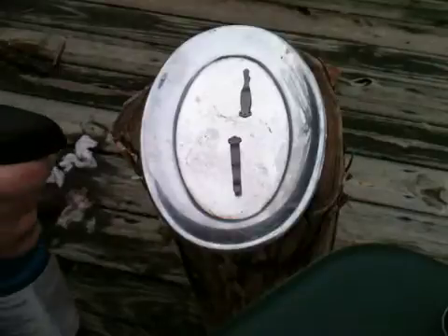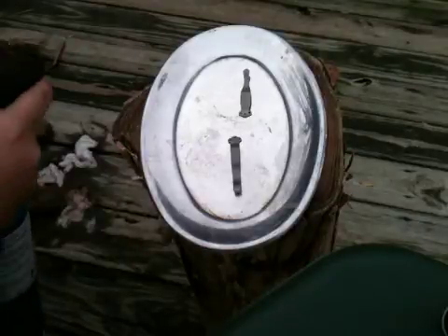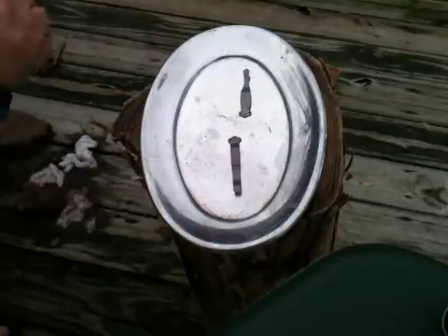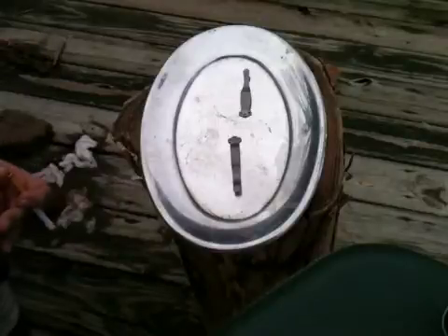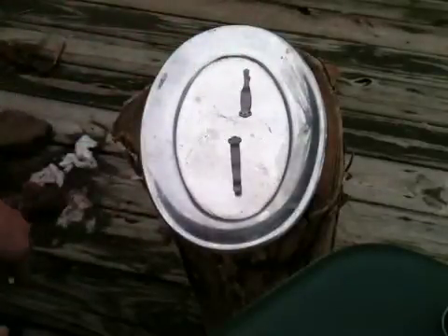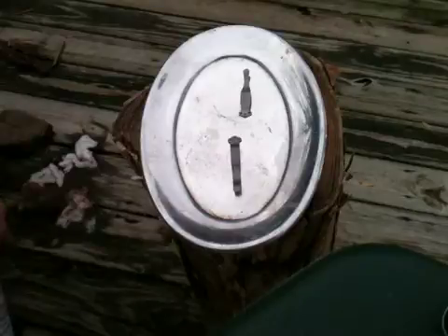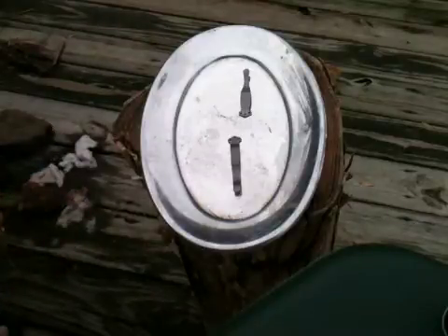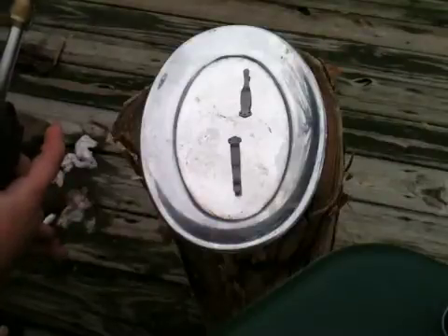Anyway, let's get right into it and see what we can do. I'm going to go for blue. One thing I didn't mention in the previous video on the spoons is that it's not just the heat that's changing the color — it's oxidizing the surface of the titanium. To oxidize, you need oxygen. When I was doing the spoons and going back and forth over a large area, oxygen was getting to the area I wasn't directing the torch on. It's when you take the heat away that the color change happens. So you give the item a little bit of heat, take the torch away, see what's going on, then go back and do it again — you slowly heat it up and watch the color changes happen.